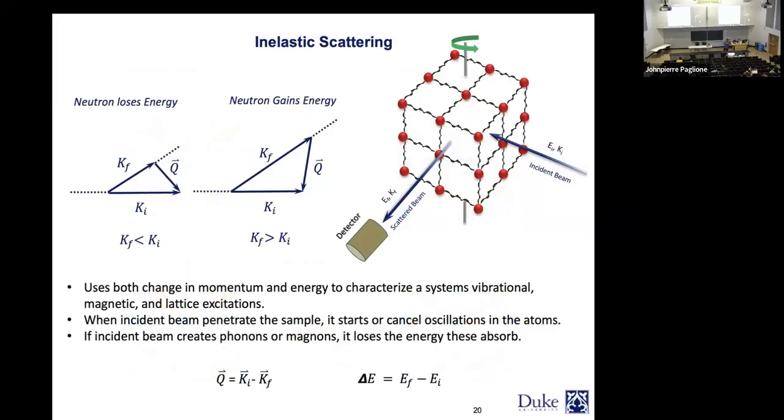With inelastic scattering, the energy of the neutron is enough for us to excite the spin energies. For example, for X-rays, we have kilo-electron volts, and the energy excitations in the compounds are typically milli-electron volts. That's why it's a little bit challenging to do, for example, inelastic X-ray scattering to probe magnetism. It's good for phonons, but for magnetism it can become a little bit challenging. But in the case of neutrons, you can tune the energy of the neutron to milli-electron volts, and then it can go in and see everything very well. And if it loses or gains some energy, it is comparable, so you would be able to calculate that.